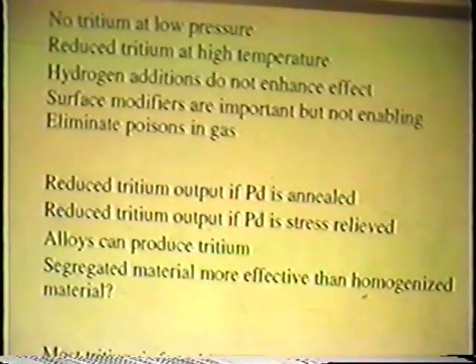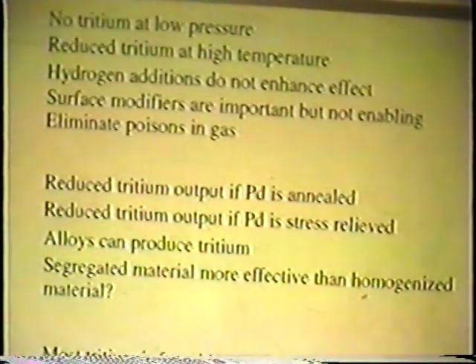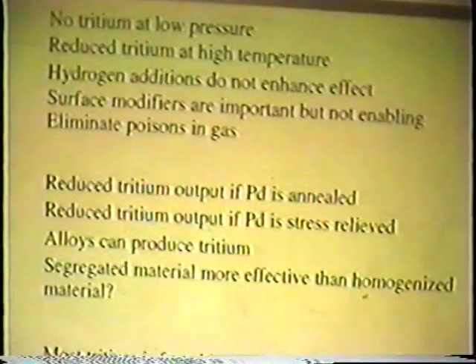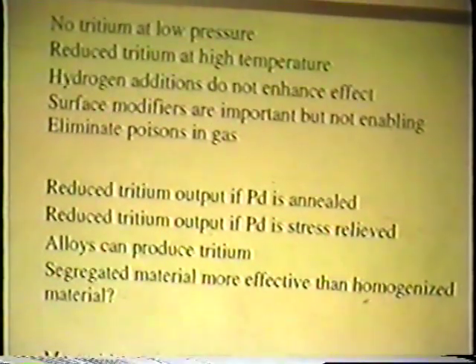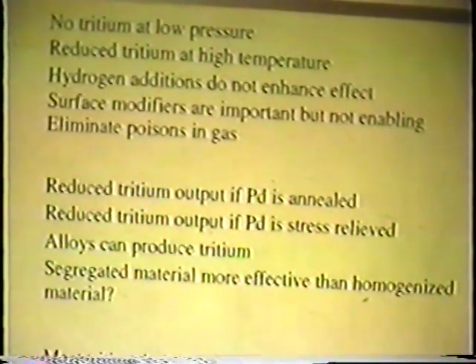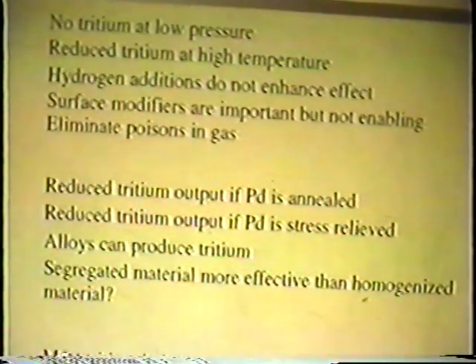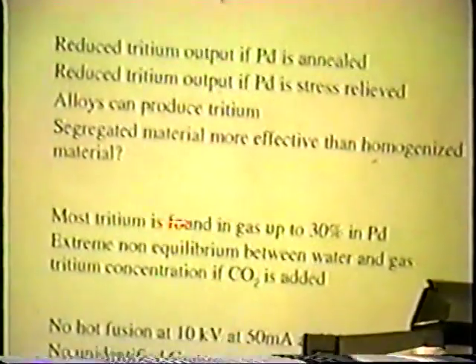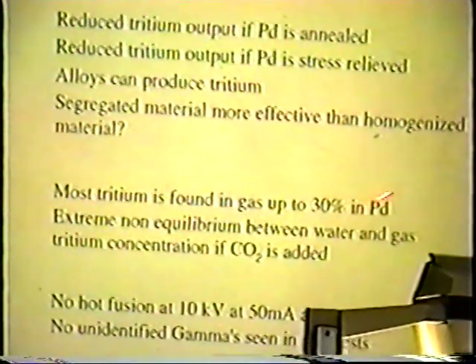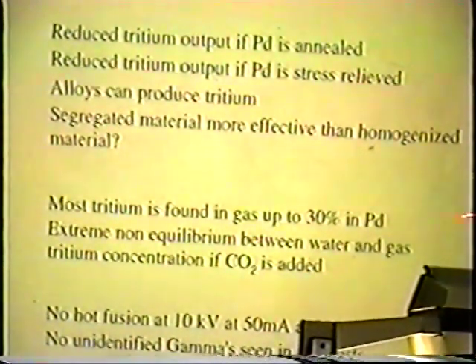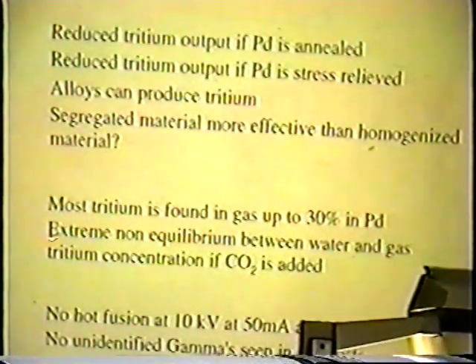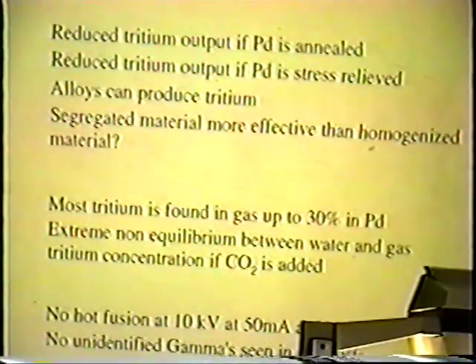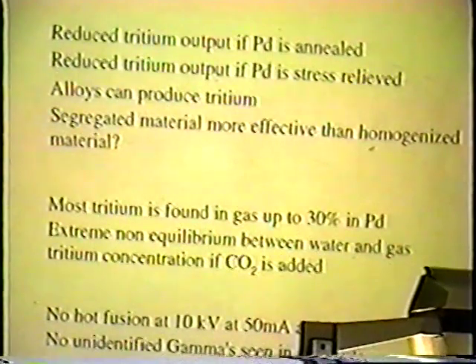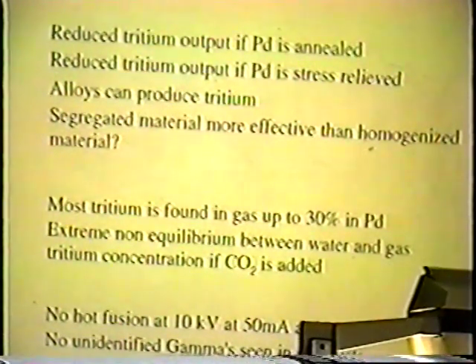Is that just because there's a lower concentration of palladium, the rhodium in the palladium, or is it because it's actually got these little islands of rhodium-rich material? Most of the tritium is found in the gas, so we're looking at surface effects here, and about 30% is found in the palladium after you dehydrate it. And we have this very large non-equilibrium between the water and the gas concentration if the CO2 is added, and we have to look at that to see what the implications there are.